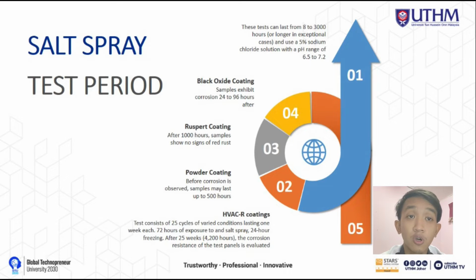Then for the Ruspert coating, after 1000 hours, the material still does not show any sign of red rust. Then for the powder coating, before the corrosion is observed, the sample basically lasts up to about 500 hours.